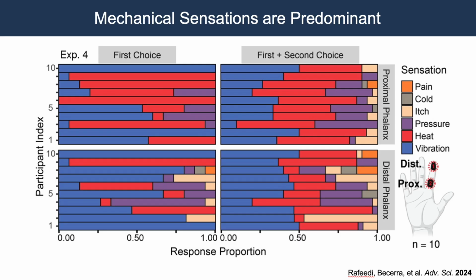And here is a workup of all the data, and this bottom left quadrant is the one I'd like to focus on, because this is the first choice sensation for all the participants at the fingertip. The fingertip is actually the most mechanically sensitive part of the hand, and so most of these participants felt the stimulation primarily as mechanical vibration. Some of them felt it as heat. So participant 9 here felt it mostly as heat, which is a bit unusual in this experiment, but not unexpected, because that thermoelastic expansion is actually mediated by heat, by the thermalization of the light.